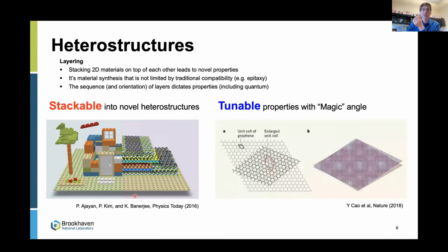So one of the fundamental reasons we care about these heterostructures is when you put one material on top of another, they're going to affect each other's electronic properties, right? So they're going to modify each other's energy levels for all the electronic interactions in that material. So they modify each other. And as you can see here, if you put two materials on top of each other and introduce a twist angle, that modification will be different because the way the atoms in the two layers line up with each other is different. So in fact, you can even put the same material on top of itself, like graphene on top of graphene, but if you control the twist angle, you can modify the electronic properties of that bilayer.